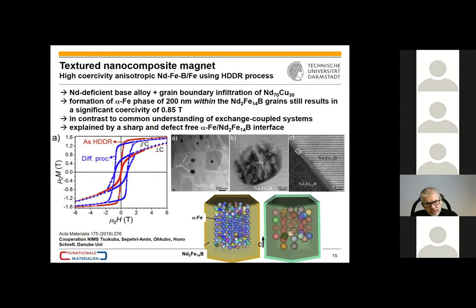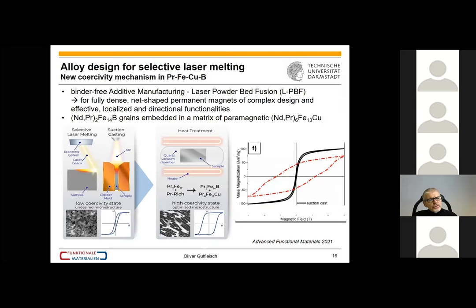Anyway, to cut this a bit short, it is interesting, and we could show that here, that we get a textured anisotropic material with iron exchange coupled, despite the fact that we get a single phase demagnetization loop, despite the fact that the iron is larger. So that we consider very promising, and we explain that with a very sharp and defect-free interface of alpha-iron to 2-14-1. And then maybe sort of in what Dieter Suess will also talk about, selective laser melting is a big challenge for rare earth intermetallics and for additive manufacturing, because we basically wipe out this nanostructure I just described.